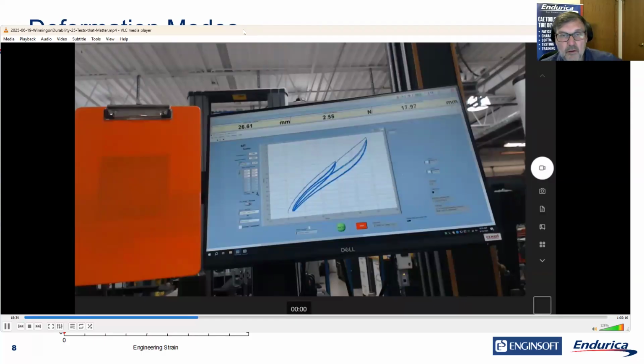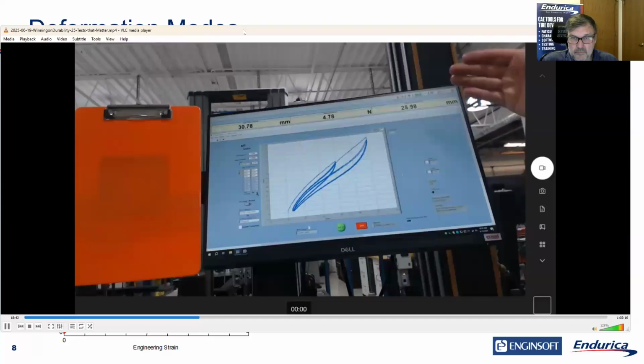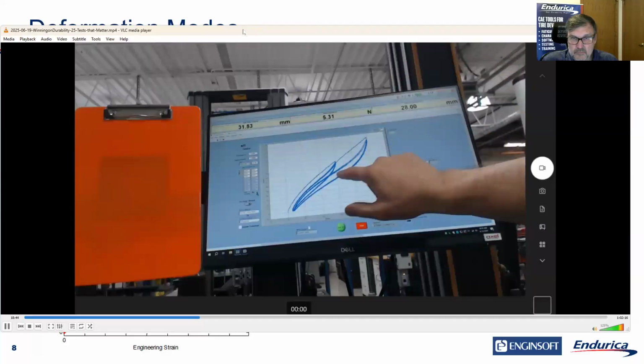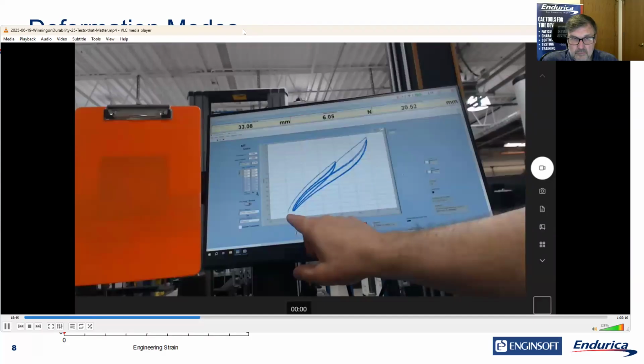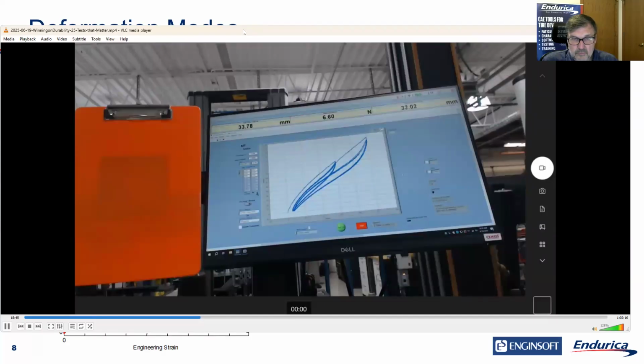So what we just saw was a tensile test, very long. When I stretch it, it's unconstrained on the sides, and we see loading behaviors. We see softening, we see viscoelastic behavior, we see a little bit of set, which we hope isn't too big, and it's going to go farther again, and I'm going to move on. I'm going to move on now to the next experiment. Talk about different states of strain.